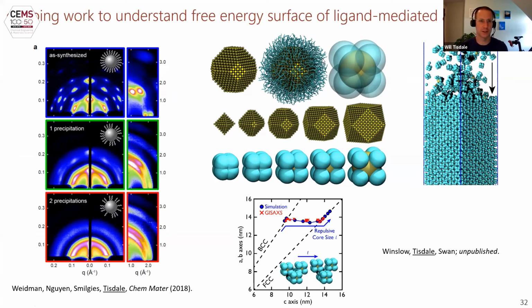But going to your second hypothesis, just having ligands on the surface doesn't tell you anything about why you should get any particular orientation. Yes, I think this has everything to do with the faceting of the nanocrystals. My particular hypothesis is that this has to do with differences in the ligand binding energy, ligand binding density on different facets. Even if you have ligands coating all surfaces, but you have a different density of ligands per unit area on two different surfaces, that effectively leads to a different compressibility.